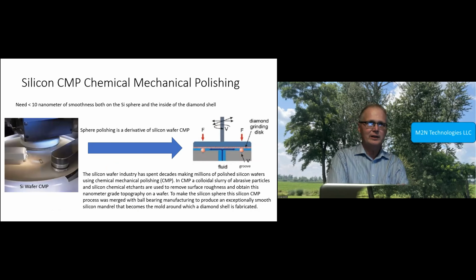The process that we highly rely on to make these extremely smooth surfaces, less than 10 nanometers of surface roughness on these spheres, just like a silicon wafer, is probably one of the smoothest surfaces that can be fabricated by man. We're taking the techniques for chemical mechanical polishing, where you have an abrasive and a chemical reaction that smooths off the surface of the structure. On the left, we're showing how it's done for flat wafers. On the right is a diagram of how it's done for these silicon spheres.